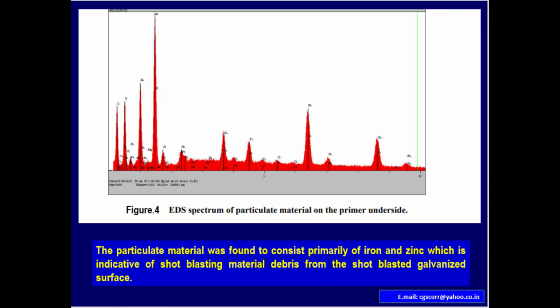Figure 4 depicts the EDS spectrum of particulate material on the primer underside. The particulate material was found to consist primarily of iron and zinc, which is indicative of shot blasting material debris from the shot blasted galvanized surface. You can see the peaks of zinc, carbon, oxygen, aluminum, silicon, iron, chromium, titanium, etc.